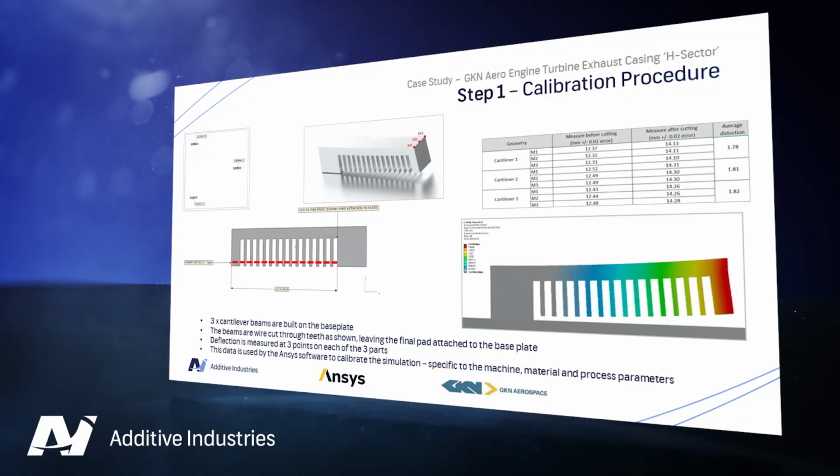So the first step is the calibration procedure, and this first step is needed in order to calibrate the simulation. So Ansys accounts for different types of analysis and different scale levels. And in this case study, we focus on the inherent strain approach. The inherent strain approach is a very effective and efficient computational method that can be used to solve complex structures like the H-Sector. These residual strains are specific to the machine, the material, and also to the process parameters that have been used to print the part, and they represent the accumulation of different strain components.